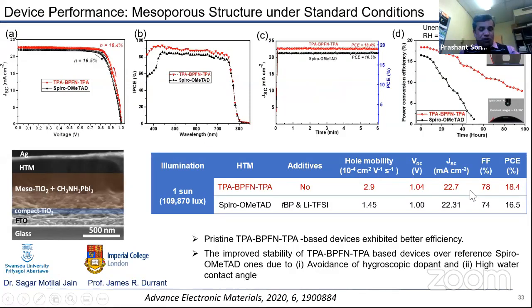Here we can achieve an efficiency of 18.4% and an open circuit voltage again more than 1 volt, and then short circuit current. And these are the IPCE and JV curves. Again, the stability data. In this case, now we could push the contact angle up to 112. In earlier cases, we got maybe 80 or 100. Now in this case, we got really the highest contact angle for the TPA-BPFN-TPA.